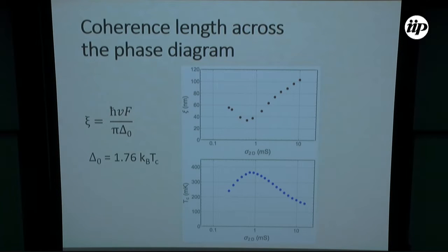Now, if we extract from the previous curves the in-plane coherence length as a function of the sheet conductance, we see that the behavior we observe reflects the relation with the gap, as we can extract from the TC. So there are no anomalies in the overdoped regime: we have both a decrease of TC and an increase of Xi, as is expected from the inverse relation. And so we don't see the presence of a pseudogap, so TC decreases, but a flattening of Xi, as has instead been proposed by tunnel experiments, where the strength of the gap remains constant in the underdoped regime.